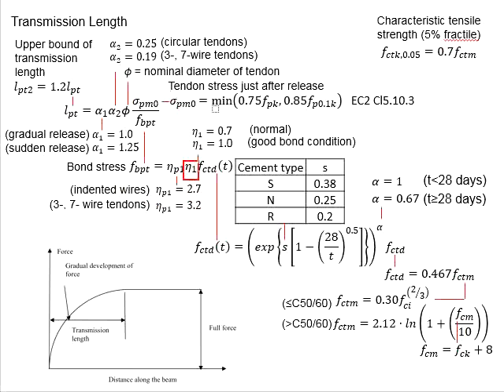The factor eta_1 represents the bond conditions. Under normal conditions, eta_1 is 0.7. If bond condition is good, you may use 1.0. Next, you need to determine f_ctd(t).